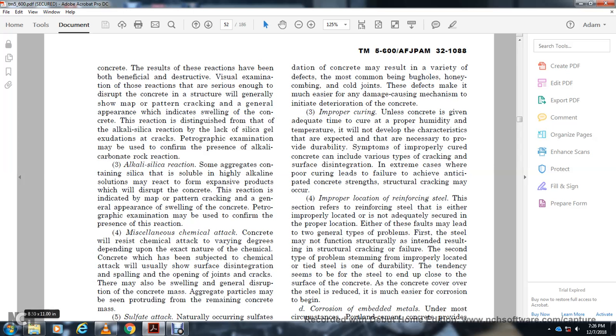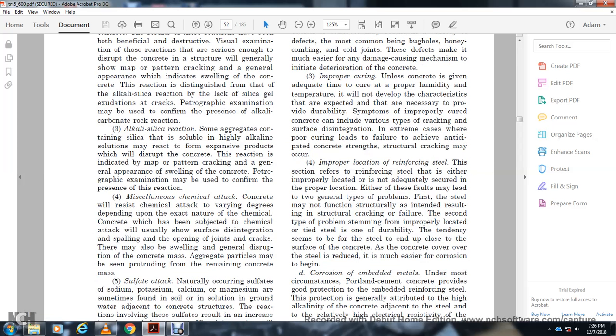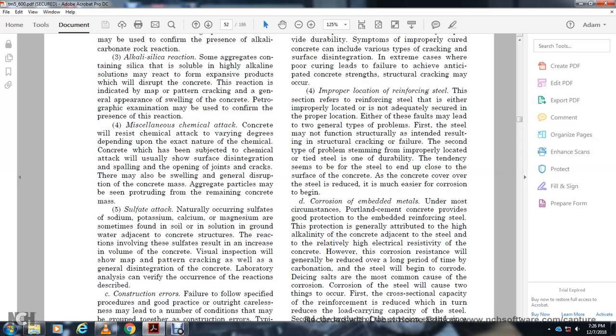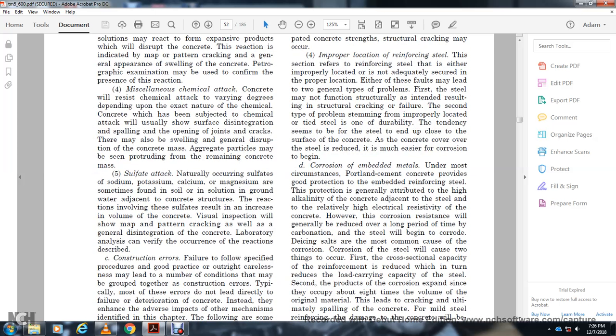Aggregate particles protrude from the remaining concrete. Sulfate attack: sulfates occur as sodium, potassium, calcium, and magnesium, sometimes found in soil or in solution in the groundwater adjacent to the concrete structure. Reactions that involve the sulfates result in an increase in the volume of the concrete. Visual inspection will show map-pattern cracking as well as general disintegration of the concrete. Laboratory analysis can verify the occurrence of the reaction described.